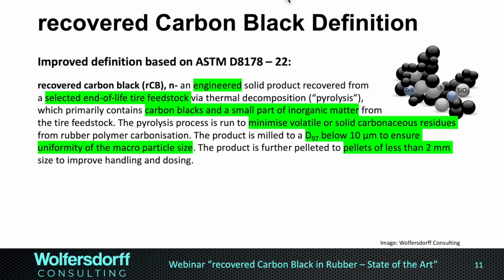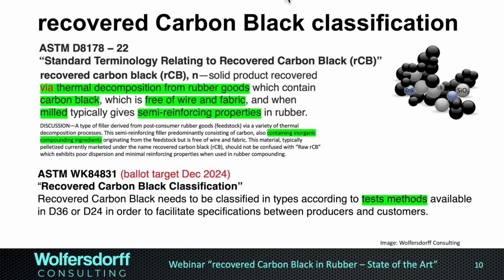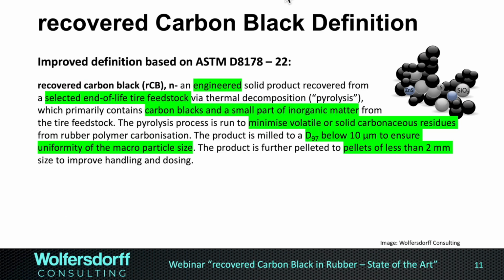So the pyrolysis process contribution is to minimize the volatile or the solid carbonaceous residues. Then we need to mill under a certain particle size. D97 means 97% of the particles are below 10 micron. And to have the uniformity of the macroparticle size. So we cannot control the primary particle size of the carbon blacks, we can only control the macroparticle size. And then of course we need to pellet, and typically the pellets are less than 2 millimeters. So that's an attempt by me improving the standard terminology relating to recovered carbon black and getting a little bit more into a product paradigm. We'll talk about that a little bit later.